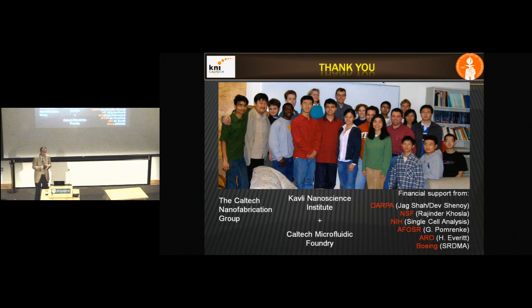So you can do that, and we've been doing that with a resolution of, say, hundreds of nanometers in the past. But my student figured out how to really control the modern reactors, which are automated. You can actually program in what they do. You don't have to sit there with a knob anymore. And so that's enabled him to get this very precise control on the order of 10 nanometers. And so it's all about the gas chemistry and the power levels in the reactor. And the precision with which you can do this is nowadays adequate to do these kinds of structures. I think it's a really neat way of making a heterostructure out of a single material.